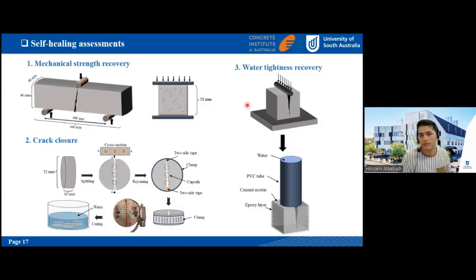Also, after the cubic samples production, we put a rebar on top to create a single crack, and then put some water on top of that and put the sample for healing. So after different times, we measure how much water penetrates through the sample. So it shows how much the healing products that will be generated can prevent the water ingress inside the samples.